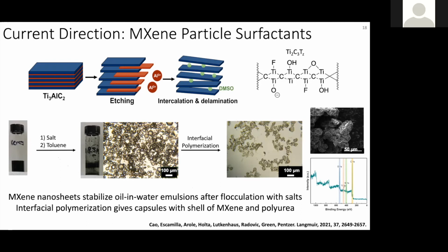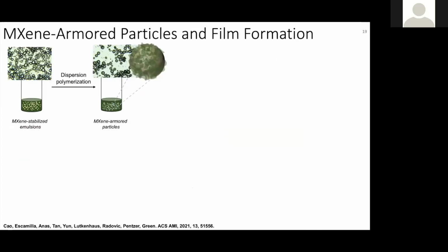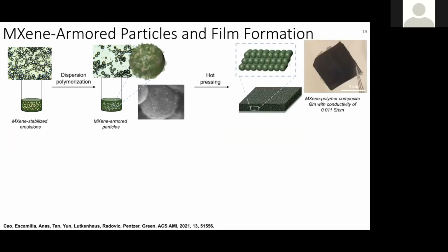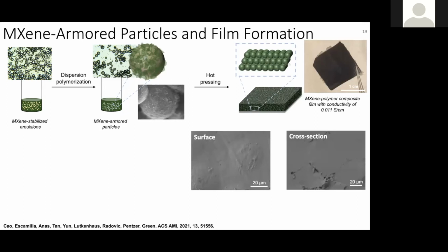We could remove that inner oil phase, and the capsule shell is composed of both MXenes and polymer. And in this case, MXenes, I should say, have a propensity to undergo oxidation to give TiO2. And so in this case, we're protecting the MXenes from oxidation. We can also do that dispersion polymerization where the oil, in this case, is styrene, to make these MXene-armored particles. We see the flaky morphology here. Then, because we're not cross-linking the polymers, we could hot press them together and make these films, if you will, with a relatively high conductivity on both the surface and the cross section.